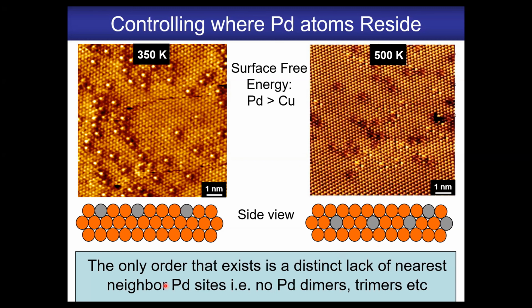The important thing here is that you don't see any long range order. You can stare at these images all day. You'll never see, at the low coverage regime, any palladium dimers in this copper surface because of that negative mixing enthalpy of palladium and copper. It would rather be surrounded by copper. So again, it's really the thermodynamics that drives the atomic dispersion.